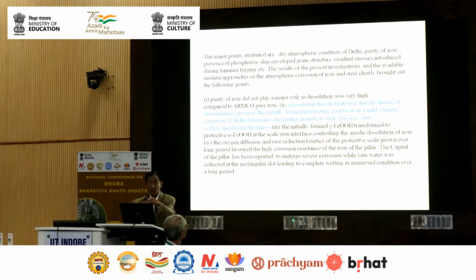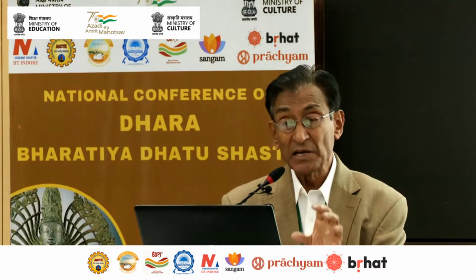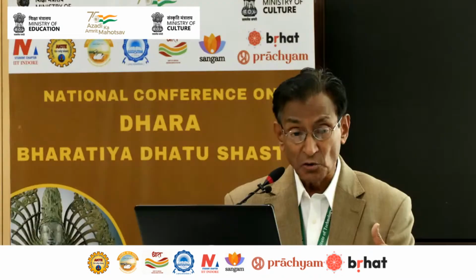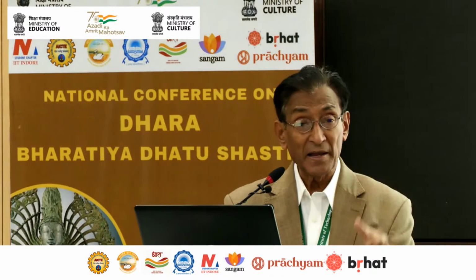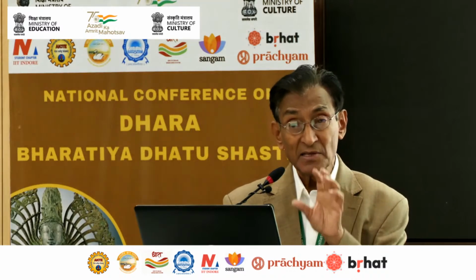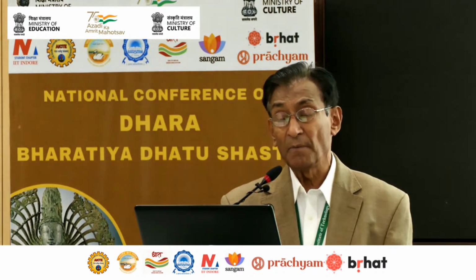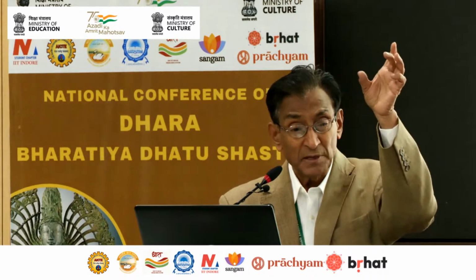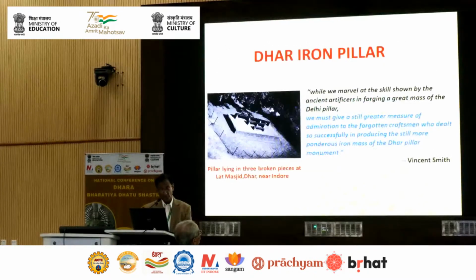That's not very important. If you go through Kamachi Mudali and Baldev Raj's work, you'll find that basically, whether it's the purity of iron or the alternate wet and dry process, initially formed gamma-FeOOH is converted to alpha-FeOOH, with oxygen's diffusion and the rust process. With all that, Delhi's distance from the seashore and the alternate wet and dry positions are attributed to the corrosion resistance. And most important, I think, the work from Kalpakam showed that the top portion of the Delhi iron pillar actually corroded extremely fast. Those data are all there, but there is no need for me to go through that.